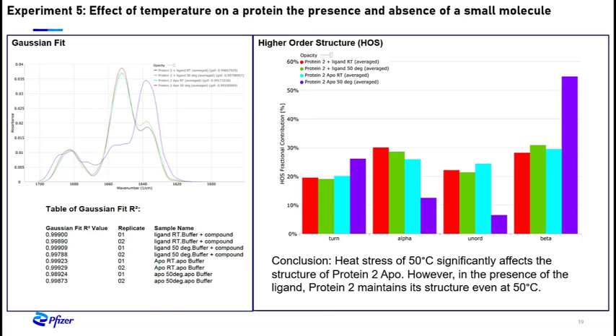And finally, our last slide from experiment 5. Here we can see on the left the Gaussian fit curve, which shows this huge secondary structure change in the apo heat-treated sample. From this curve, we generate the higher order structure bar graph, which depicts the changes amongst the 4 different samples very nicely. Again, you can see that heat has significantly stressed the protein without ligand, while its ligand-bound counterpart has been reasonably spared.